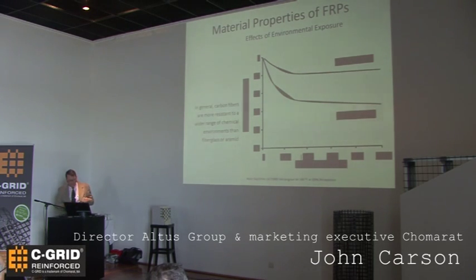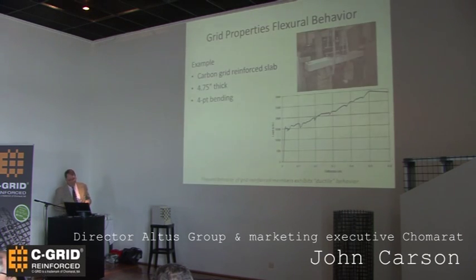Unlike glass structures, which see onset of alkali deterioration over time and loss of properties to the magnitude of somewhere in the neighborhood of 60%. So considerably different, and also the carbon fiber is much stronger.